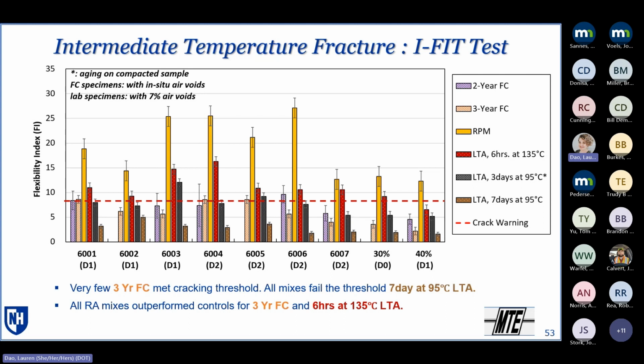Basically the takeaway from this is that once we hit the 3-year aging, we're below that threshold of 8. Now that flexibility index threshold of 8 is based on an unaged material. But once we're aging, we're dropping down below that pretty quickly. You can see most of the reheated plant mix well above that. But then once you start aging these, especially getting to the 7 days aging, you're at a point where practically none of these mixes are any different from each other.